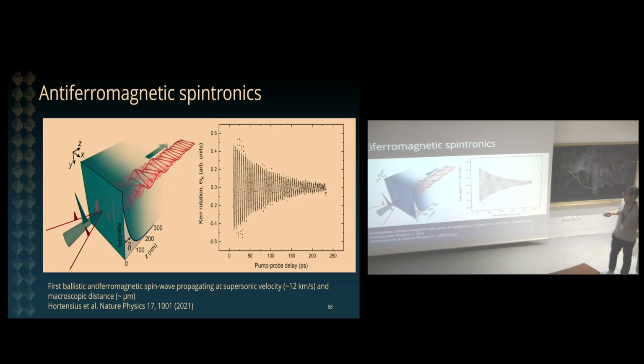A final experimental point: you can ask for how long this propagating wave travels. So you can just sit and let it ring down. We are lucky that in this high temperature non-collinear antiferromagnetic state, magnons are very long lived in the system. So we can track this oscillation for a long time, and we see that for hundreds of picoseconds this keeps ringing. We have a velocity of this propagating wave packet, so we can estimate the distance over which this wave is traveling, and we find something of the order of a micron. So these waves propagate ballistically with a velocity that is supersonic, 3 times the speed of sound, 12 kilometers per second, and they propagate over macroscopic distances.